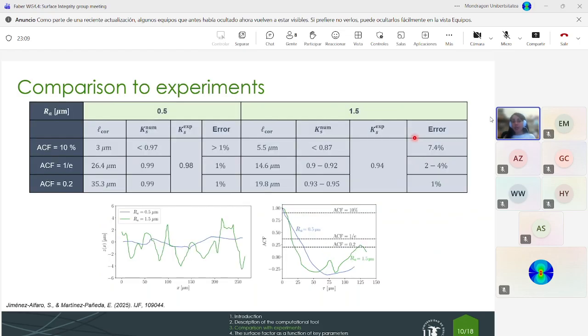So our numerical tool can be more accurate if we know the correlation length, and this is what we have done here, because in the experimental campaign done in 2019, we have also the surface profile, as you can see here. So we have used this surface profile to build the ACF, the autocorrelation function, and then we have determined, using the three criteria, the values of the correlation length. So you can see here the results.